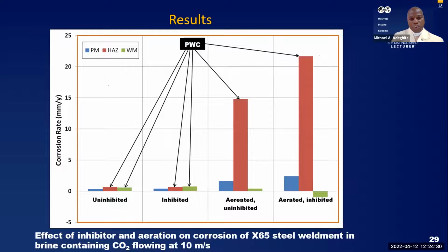flowing condition. So the same result is being displayed, and we can see in a flowing condition there is a challenge of preferential weld corrosion. Anytime there is flow, preferential weld corrosion can occur, and that is usually taken for granted that it cannot occur, and that's why we have this challenge. We can now see that anytime there is flow, we can have this challenge.